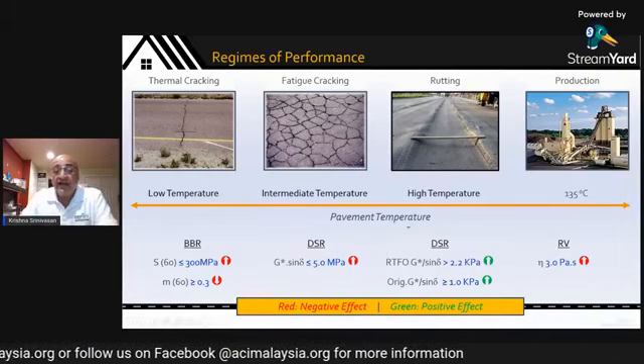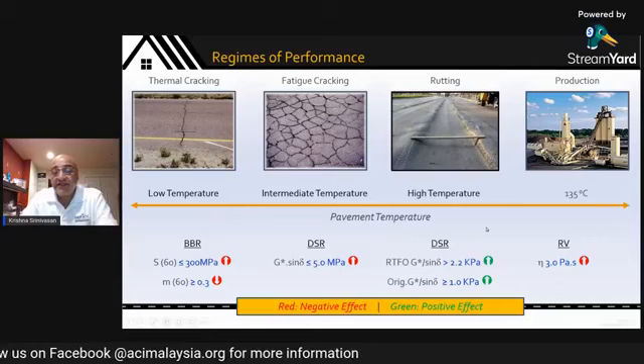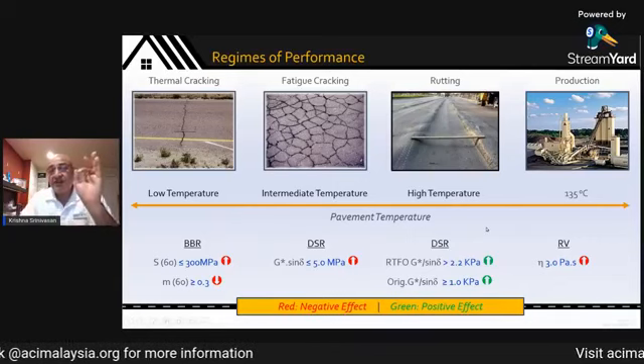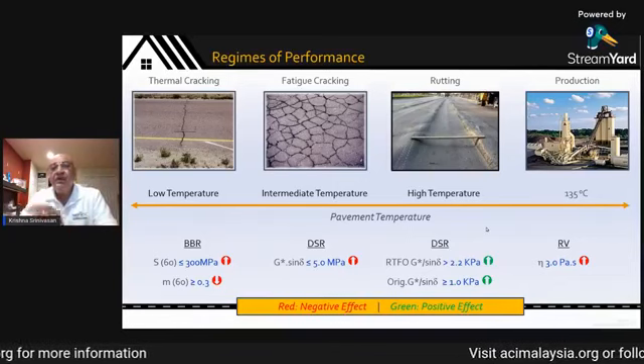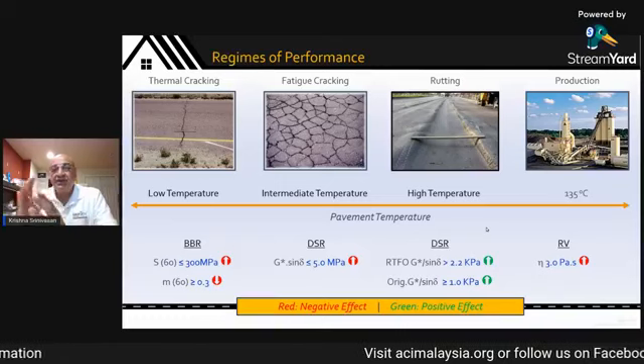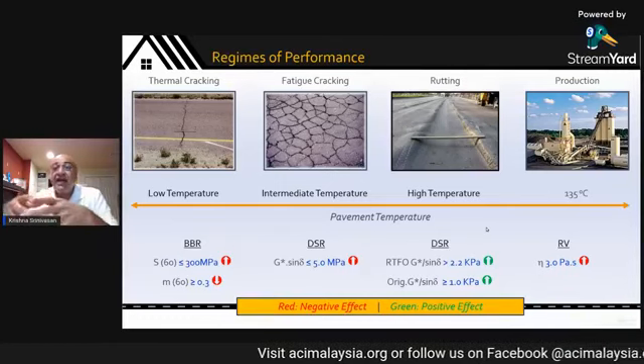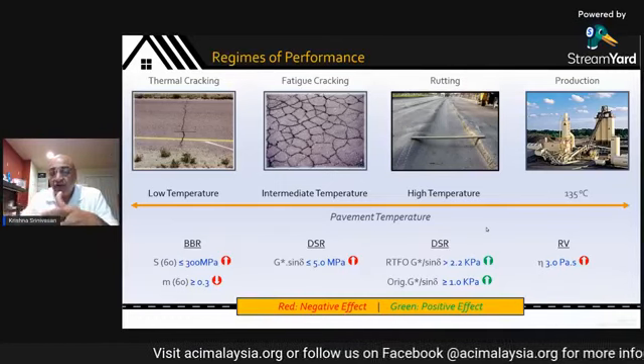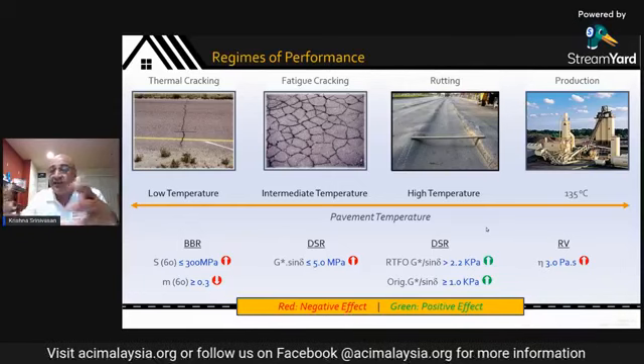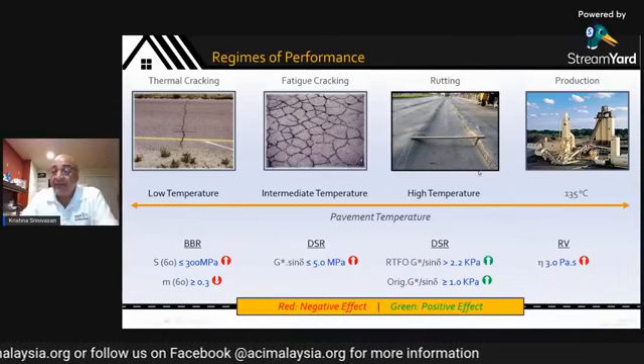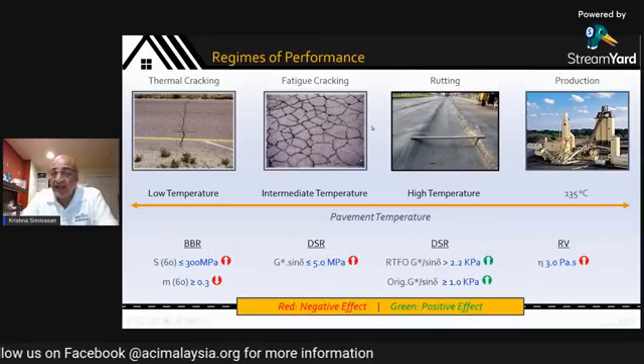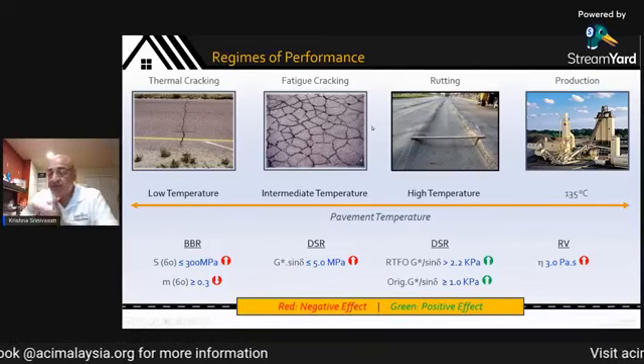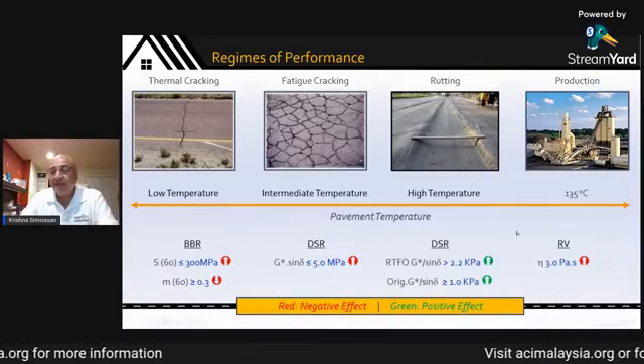Rutting, on the other hand, as measured by these parameters, is worst on day one. On day one, when you put down your pavement, your mix is a little bit soft. As it becomes more stiff, more brittle over time, the rutting performance keeps on increasing. And RAP, reclaimed asphalt pavement, helps with rutting performance. And we'll go into that in a little bit of detail.